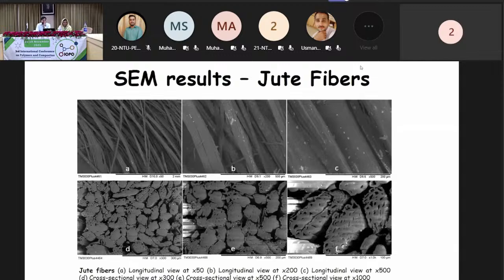Due to the SEM results of jute fibers, as you can see here, with 50 times, 200 times, 500 times longitudinal magnification, and also cross-sectional view with 300, 500, and 1,000 times magnification, jute fibers are straight and cylindrical. They have a hollow structure, and also jute fibers have some notches on their surface.